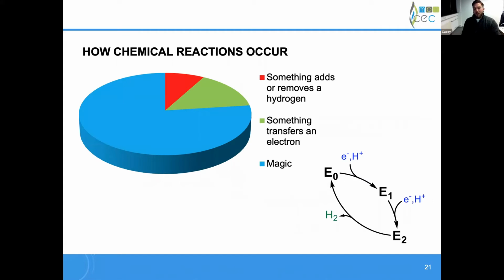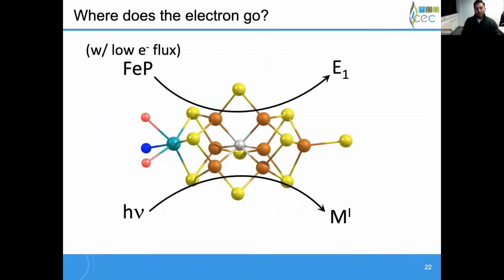Now, if we look at their conclusions, this was all based on the assumption for the Mössbauer that we have a 1 electron difference. But when we go from E0 to E1, we don't just add an electron, but we also add a proton. And so maybe the difference between generating our actual E1 state and generating this cryoreduced state that they observed is not a true difference in the location of reduction, but is actually just a difference in whether or not the cluster has been protonated.